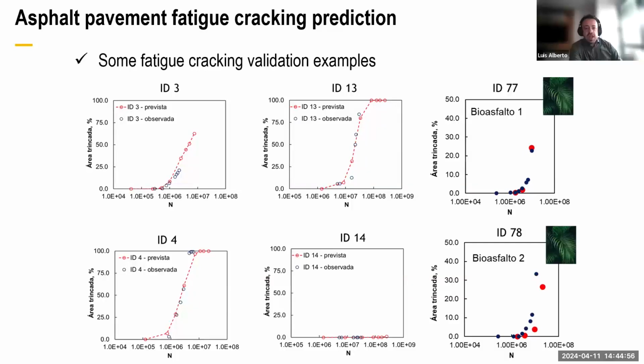No. Actually, this is a very nice question. Thank you. We have more than 50 national test sections and around 24 test sections in our FUNDAM project. So the transfer function is only one for all test sections, only one transfer function. Once you run the analysis, we use the climate data for the test sections, the material properties, the traffic pattern. So we run the simulation. Once you get the computation analysis, we use the transfer function to predict the cracked area. But the transfer function is the same for all the experiments. It's only one transfer function.